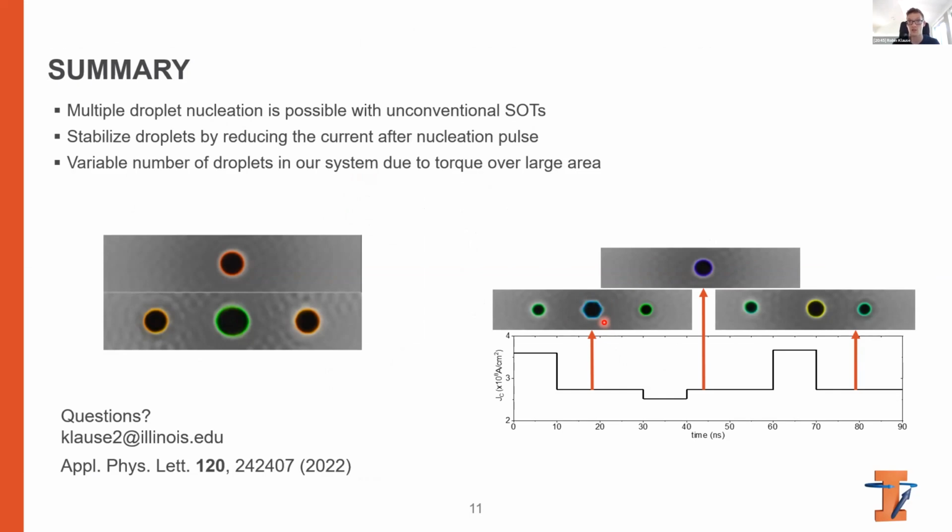So with smaller magnetic fields, they tend to be more elliptical when they grow, and with larger fields they tend to be more hexagonal, and in between it's like a triangular structure. So I think these correspond to different frequency modes in the droplet.